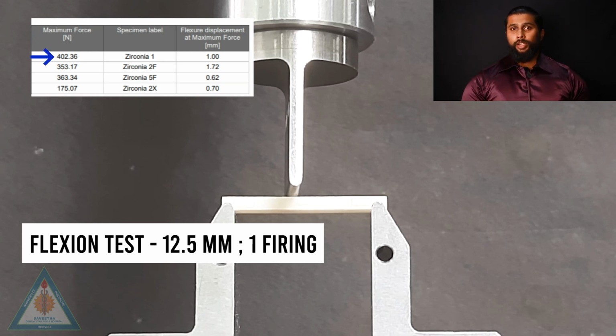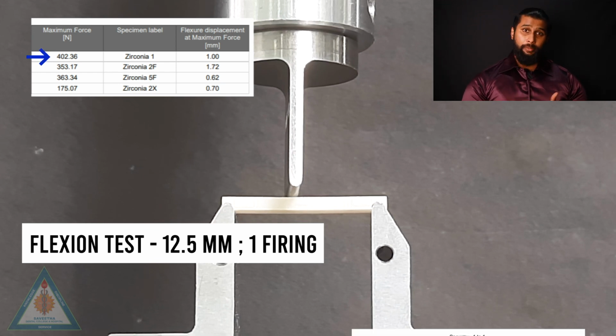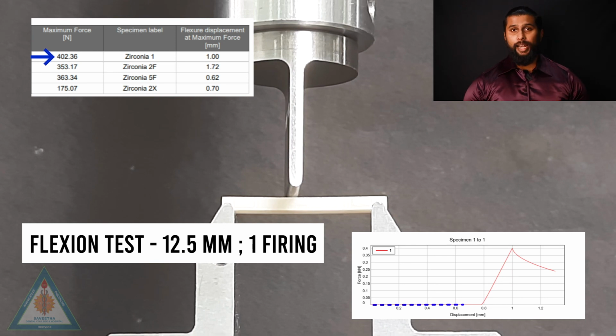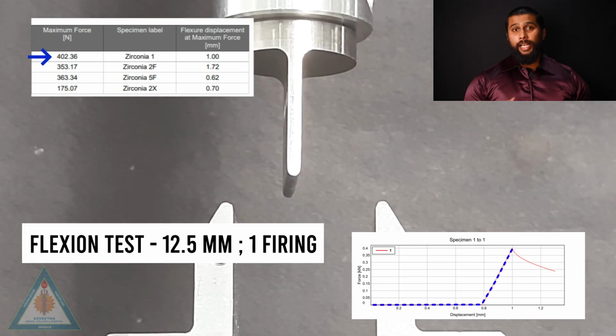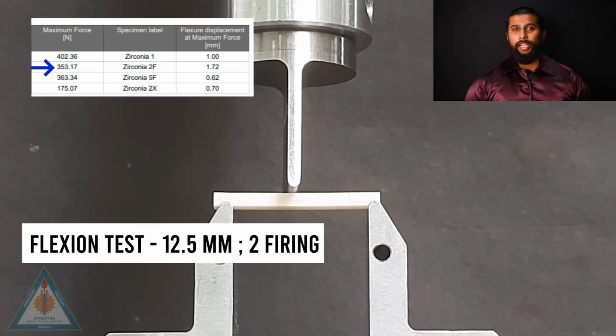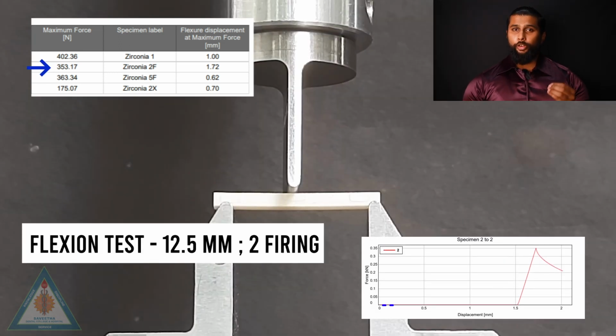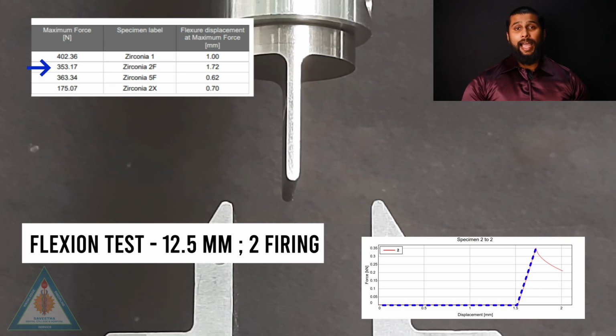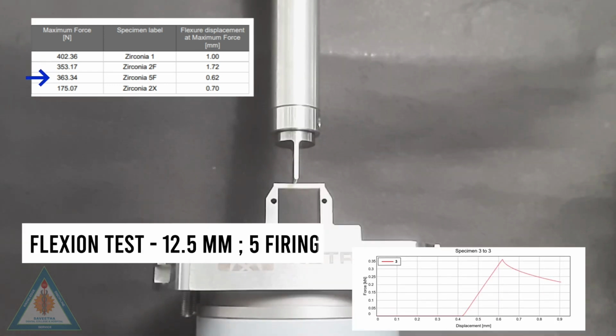in the middle. Now, we threw on some samples that were sintered 1, 2, 5 times and another sample of twice the length. Now, what we found out is that the flexural strengths dropped in the samples that had been sintered 2 and 5 times. This is due to the development of microvoids within the zirconia crystal as it is fired again and again.